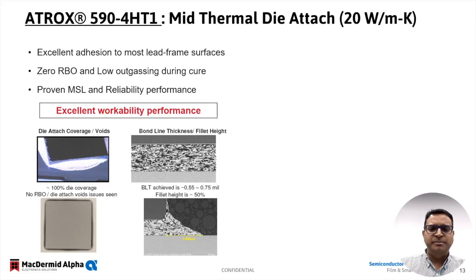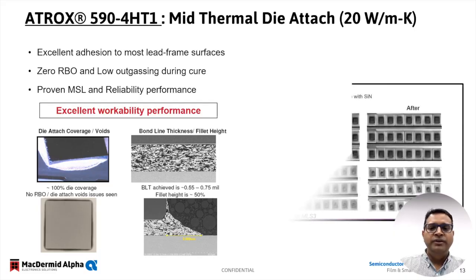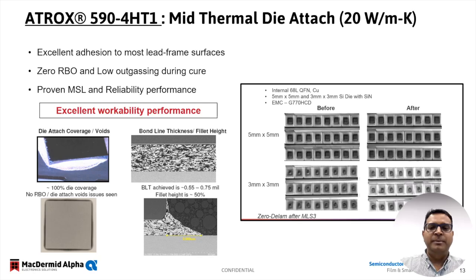It is especially critical in products like these, which provide high thermal conductivity, to provide good dispensability and workability at the same time, considering the high filler loading that they need to achieve the high thermal conductivity. On the right hand side here, we have some MSL data that proves high reliability, where we can see there is no delamination observed after exposure in MSL3 environment.